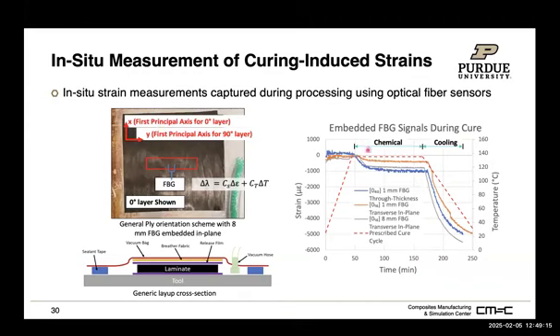Something you will observe here is what we call the prepreg, where you already have the polymer in your fiber, but we try to insert the optical fiber sensor transverse to the fiber. So we measure what we call the polymer-dominated behavior. Something we observe from the optical fiber sensor is that there is indeed a shrinkage that occurs while we have constant temperature, right?